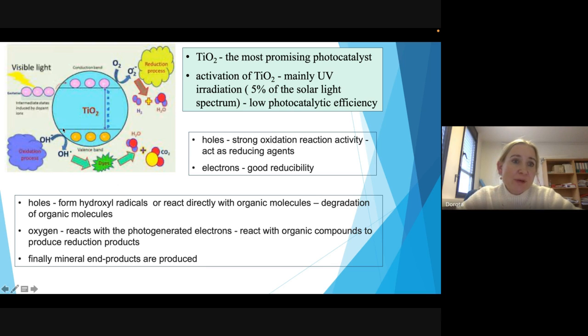How it works: when we illuminate our titanium dioxide, electrons from the valence band are transferred to the conduction band. The holes that are left in the valence band react with water molecules and produce so-called hydroxyl radicals that react with the contaminants in the water, the organic compounds, and cause their degradation. On the other side, the electrons in the conduction band react with the oxygen that must be added to the water all the time, and produce oxygen radicals that also react with the organic compounds. Finally, both these radicals degrade our pollutant, forming mineral end products.